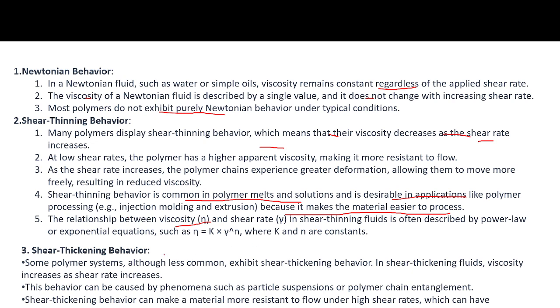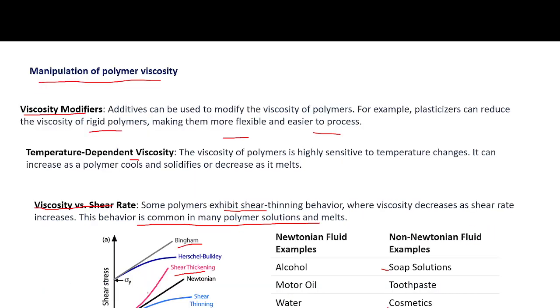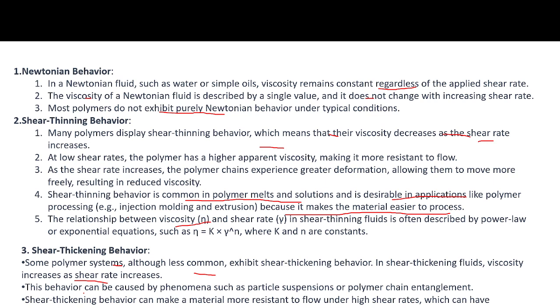Shear thickening behavior: some polymer systems, although less common, exhibit shear thickening behavior. In shear thickening fluids, the viscosity increases with the shear rate, or shear stress increases with increasing shear rate, as shown in the figure. This behavior can be caused by phenomena such as particle suspension or polymer chain entanglement. Shear thickening behavior can make a material more resistant to flow under high shear rate, which can be an advantage in certain applications such as body armor and damping materials.